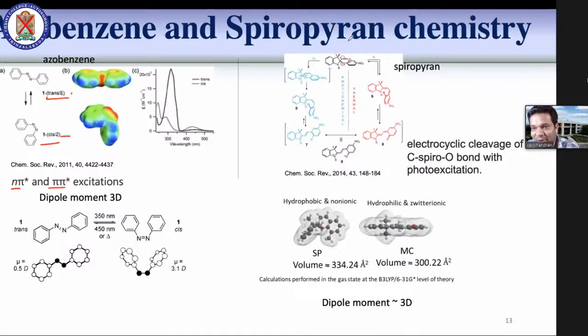When we come to spiropyran chemistry, this is an organic heterocyclic compound. With photo excitation, there is heterolytic cleavage of the C spiro O bond, and it goes from the ring-closed to the ring-opened structure, from hydrophobic to the hydrophilic merocyanine structure. The chemical property change is not just hydropolarity; there is also a small change in the volume of the spiropyran and merocyanine molecules.